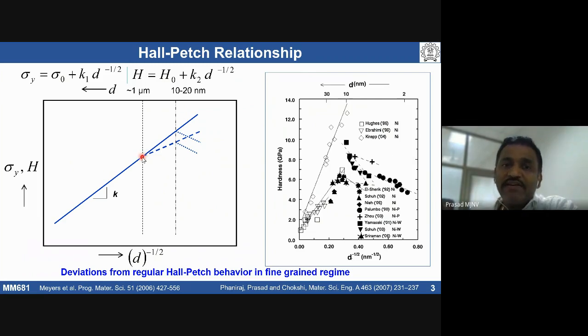However, in the last 3 decades, there's been a huge amount of experimental work that has gone into producing fine grain size materials. When people started producing fine grain size materials less than 1 micrometer, they reported deviations from the regular Hall-Petch behavior. So the deviations can be a change in slope, meaning K can be changing, and this deviation can also undergo an inverse kind of thing.